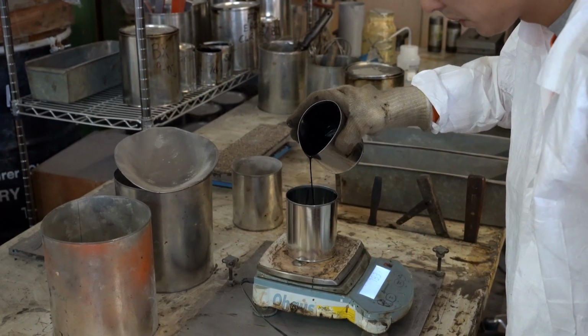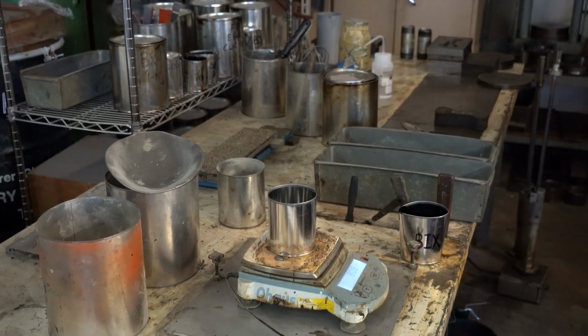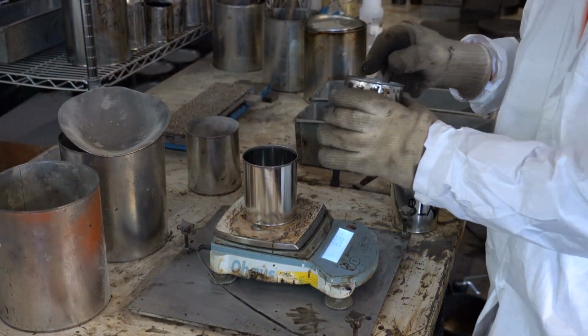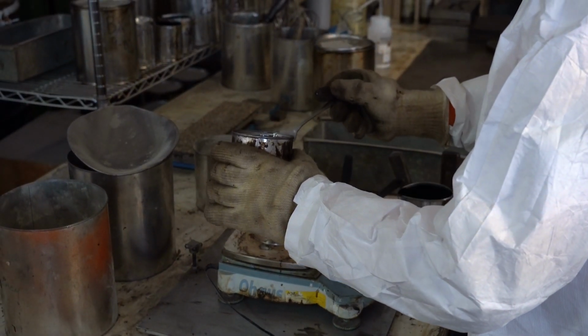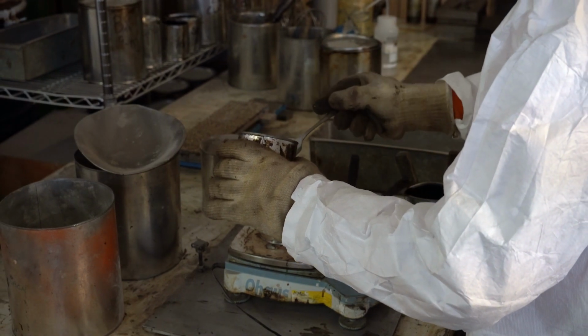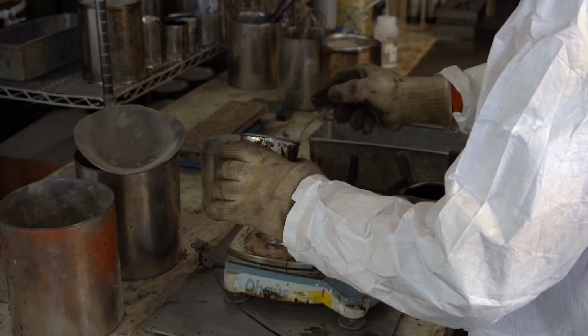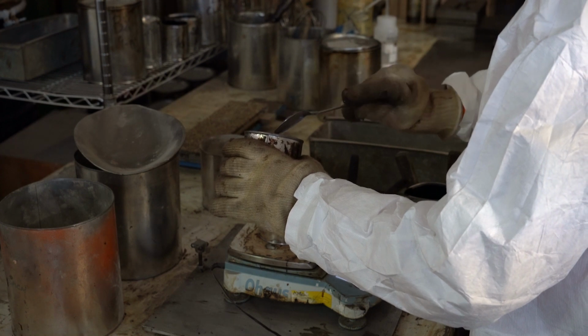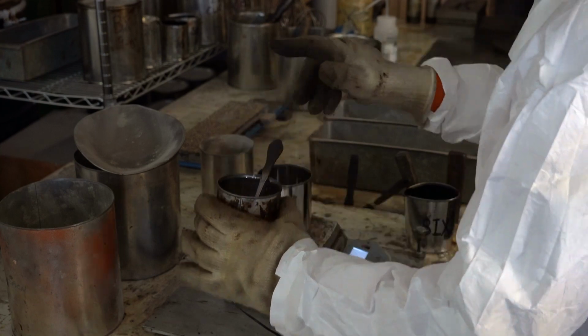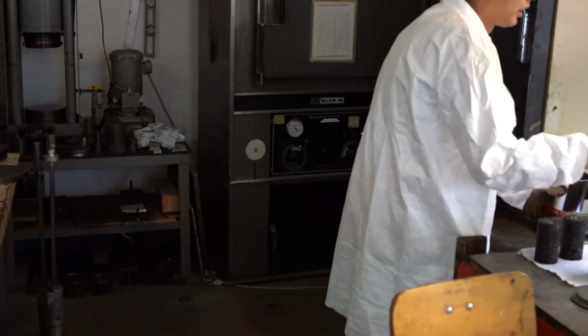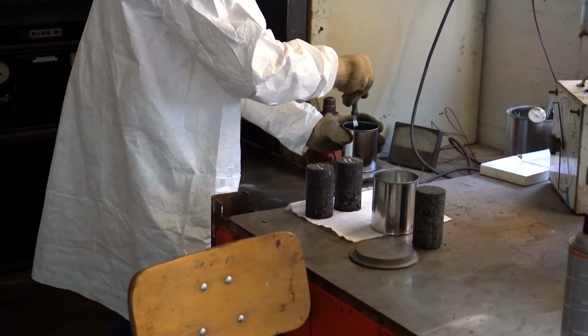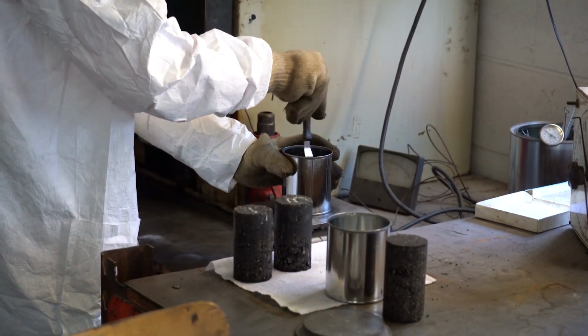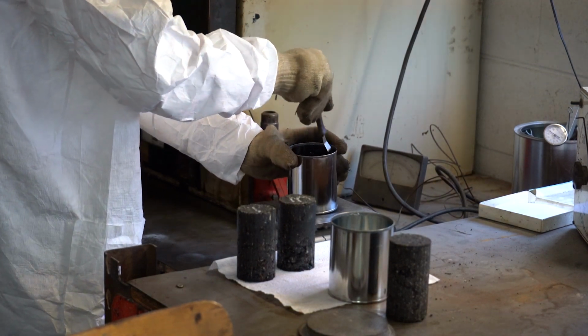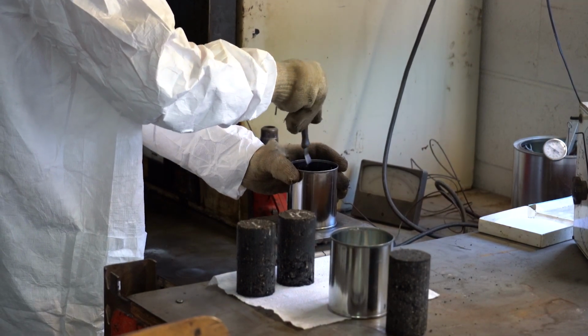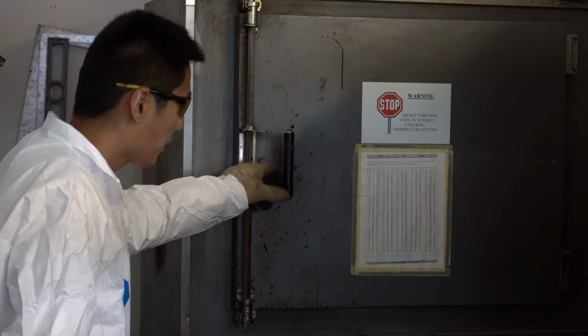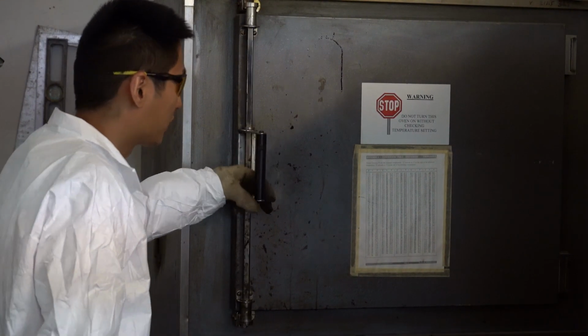That's 80.66, and with part A in the right ratio. And we put it on the hot plate, turn on the timer, and we mix for about a minute and a half to 2 minutes by hand to make sure the part B and part A are mixed properly. Okay, oven, and we set the temperature at 280 Fahrenheit, which is about 140 C.